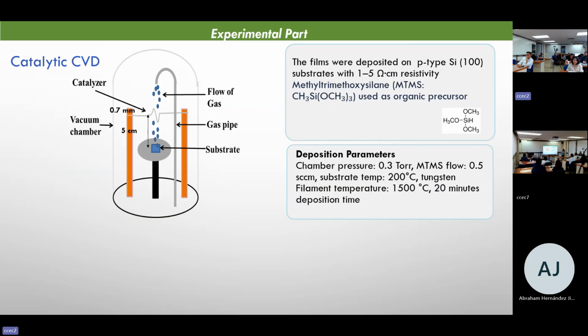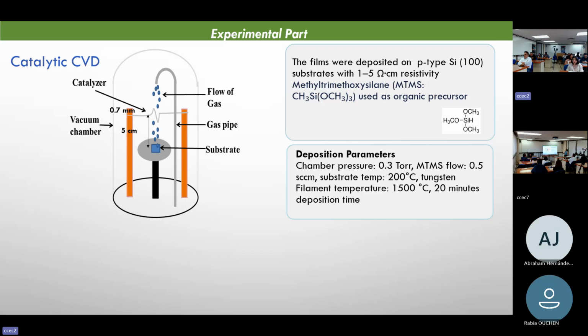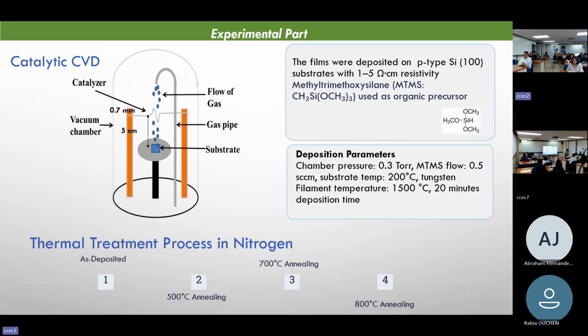And this diagram shows the system we used. The films were deposited on silicon substrates with 1 to 5 ohm centimeters. Chamber pressure 0.3 torr, MTMS flow 0.5 sccm, substrate temperature 200 degrees Celsius, tungsten filament at 1,500 degrees Celsius for 20 minutes. And the thermal treatment process in nitrogen was done.